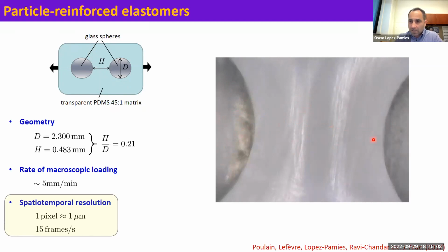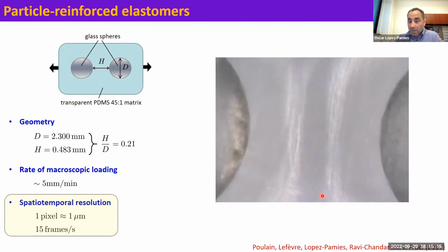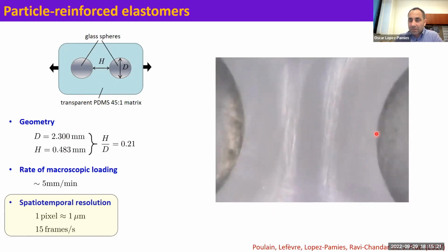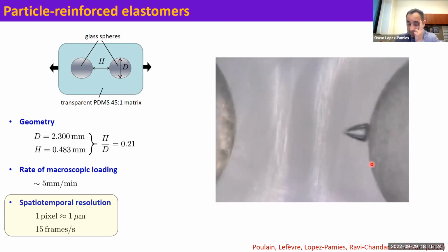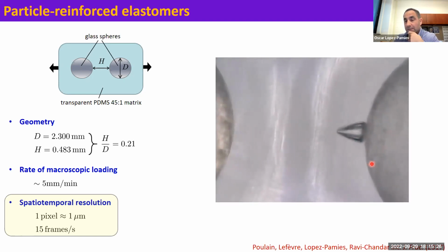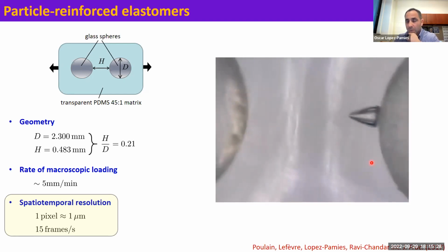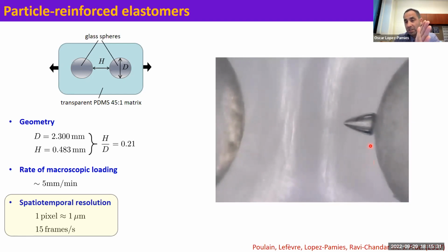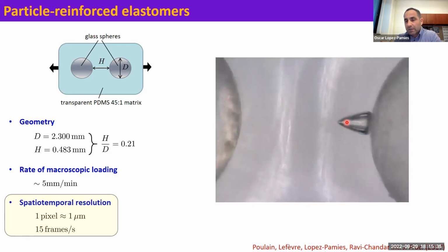So I'm going to play the movie. What we are doing to this specimen is simplifying, in the sense that you only have 2 particles instead of many, but they're very close to one another. You can see here the dimensions. So what happens is that you are going to nucleate a crack near one of the poles. That's a crack, but it doesn't look like a crack because we are looking at the deformed configuration. So when you deform a penny-shaped crack between something stiff and something soft, it deforms